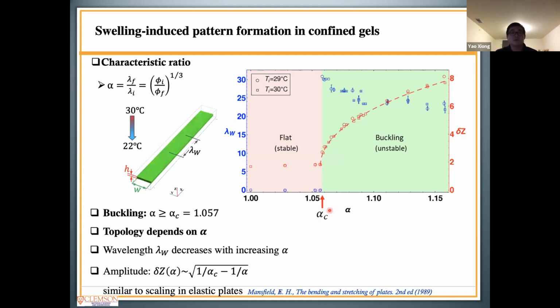We also find that beyond the critical point, increasing the alpha results in the decrease of wavelength and the increase of amplitude. And the amplitude has a relationship between the alpha c and the alpha. Based on the linear elasticity, this part is related to the compression applied on gels by boundaries. A similar dependence of amplitude on the compression was also found in elastic plate.